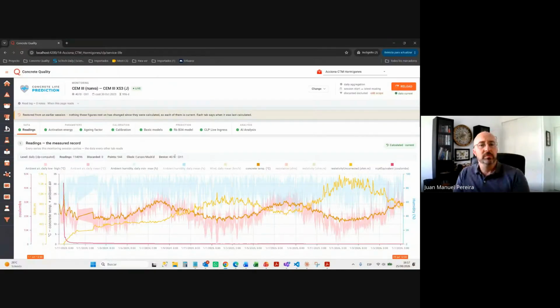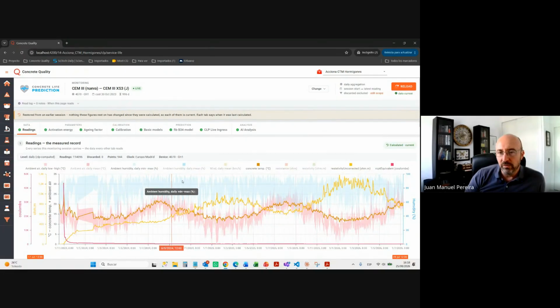So here, okay, and this is one of these port structures you've seen, these blocks. This is the one that is with Cemex. This is a blend with GGBS. Okay, like maybe 40% replacement of the clinker with GGBS, and exposure class, the most demanding, which is the tidal. Okay, because it dries and wets. Okay, so what we see here is almost 1,000 days of readings, which you can see here in this graph. Okay, we have weather information, we have moisture. This is a very moist area. Okay, the city itself is very moist. We have ambient temperature. Okay, we gather all the weather information as well.